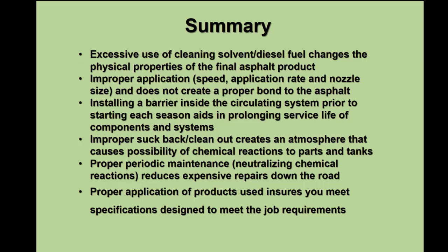Conversely, at the end of the season, you need to clean that tank out. People that don't have the availability to flush it with a hot material, that's fine, but you can flush it with just plain water. Water will dilute the hydrochloric acid and stop the eating of the tank. Improper suck back and clean out creates an atmosphere that causes possible chemical reactions to parts of the tank. Neutralizing chemical reaction reduces expensive repairs down the road. But the most critical is that proper application of products used ensures you meet specifications designed to meet the job requirements.